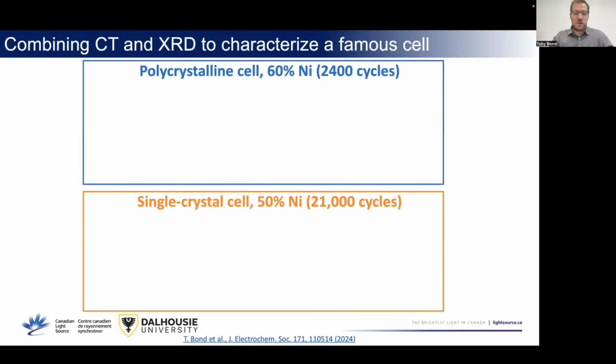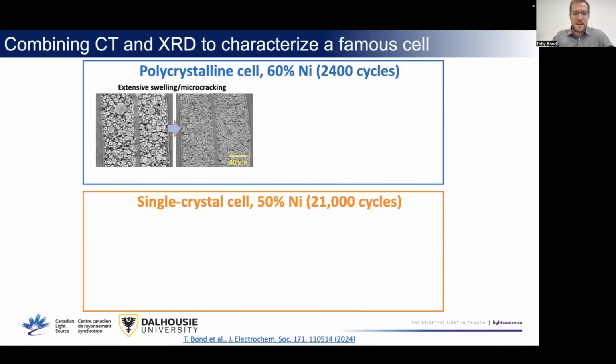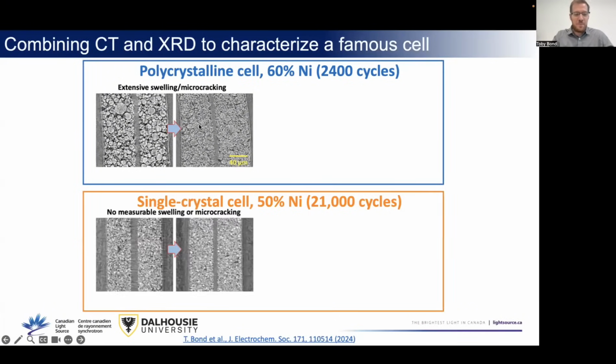But we really want to look under the hood and see, how does the cell look? Did it also get pulverized? Is it at 80% but could fail any minute? Well, if we compare this to the data we just looked at, where you have this extensive swelling from the fresh cell to the cycled cell, in the single crystal material, there's no change.